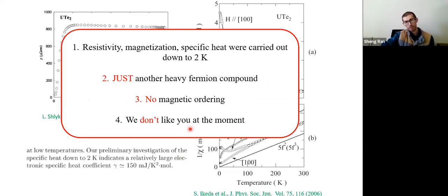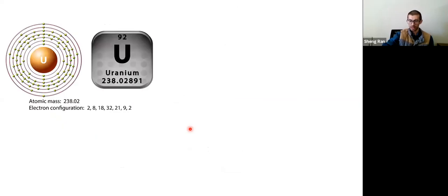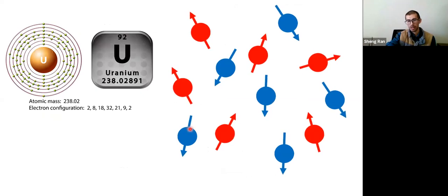But if you think about this a little bit more carefully, it's a boring system, but it's interestingly boring in the sense that it contains uranium. For those who are not familiar with this, uranium is at the bottom of the periodic table, where everything contains f electrons. At a higher temperature, all these f electrons point in all kinds of directions. But the system wants to release entropy at a lower temperature. Now, of course, the Kondo effect is one way to lose entropy, but given that gamma is only 150, it's large, but not that large, it really indicates there are still unscreened moments.